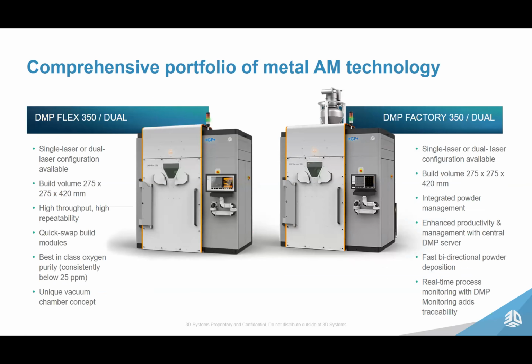All right, now these alloys are printable on our mid-frame systems, DMP Flex 350 and Factory 350, not yet available on our large frame system. Pure copper is in fact using a different optical configuration, and there's a good reason for that. As Jacob mentioned, there are ways to print it with a standard optical configuration, and we did prove that too. But in order to really get the productivity and speed for production applications that our customers are demanding, we did go with a different optical configuration, and that actually benefits us in the end result.